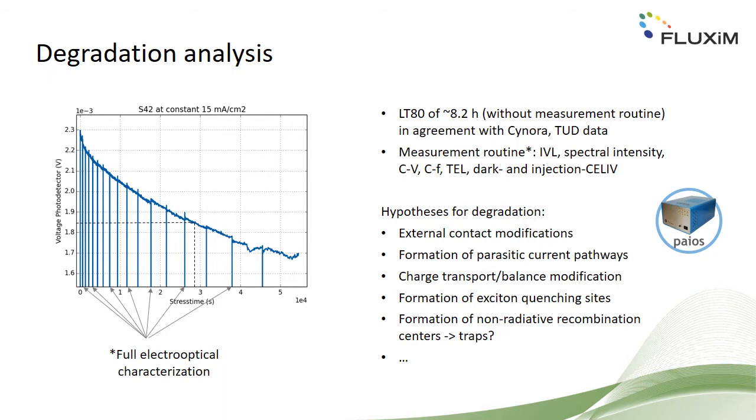In the second part of this study, we analyzed the degradation behavior of the TADF OLED. The OLED was stressed at a current density of 15 milliamps per square centimeter, while the voltage and luminance were recorded, as shown on this graph. At specific points in time, a full measurement routine was performed, including IVL, CV, CF, transient EL, dark injection, CELIV. Together with the device simulation, this comprehensive dataset allowed us to investigate different